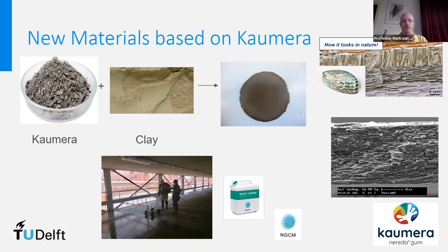Now, with biopolymers, not only with Kaumera, also with alginate, with chitosan, and other biopolymers, we have seen that we can go to much higher amounts. So we can go to 85% of filler and only 15% of polymer. And with that, we can make a natural composite material which resembles, for instance, shells.